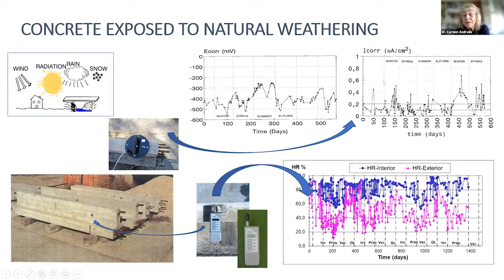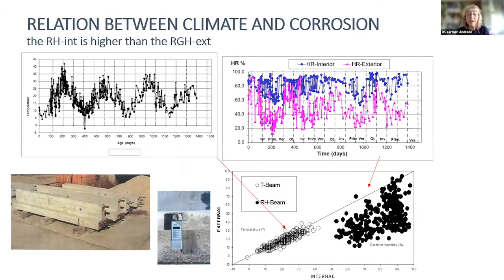The relative humidity, parallel to these values, is plotted here, and we realize that externally the humidity is lowering and going up, that we have the daily change in relative humidity and the seasonal change in relative humidity. But inside the concrete, the relative humidity is much higher than externally, even in the very dry periods that we have in summer in Madrid. And when we compared that with the temperature, we realized that the humidity is moving in a mirror manner with the external relative humidity. While the temperature inside and outside the concrete is very similar, the relative humidity, as I said, is completely different. In that case, it is much wetter inside.